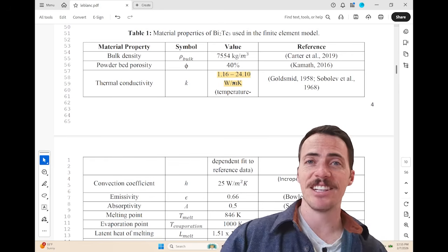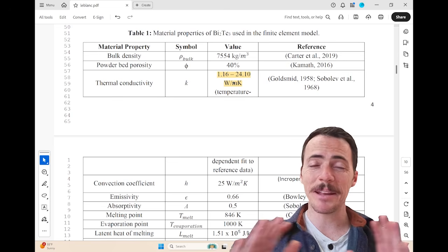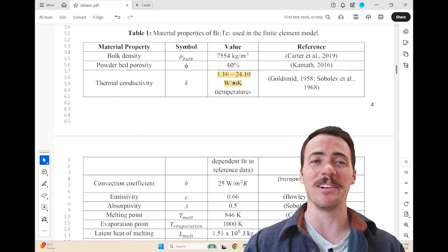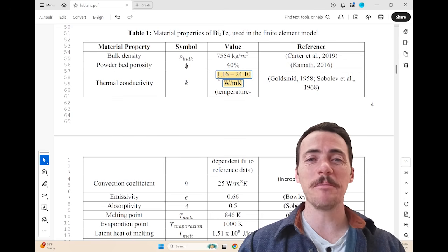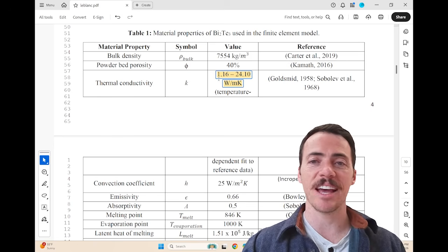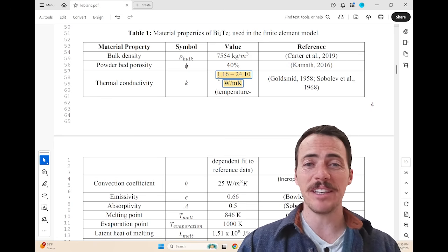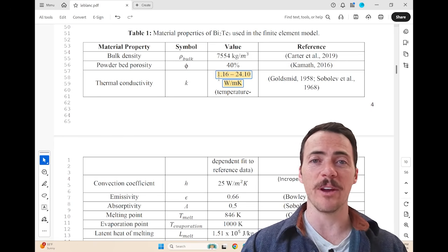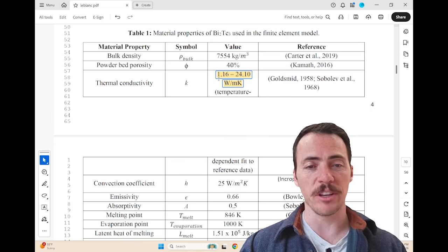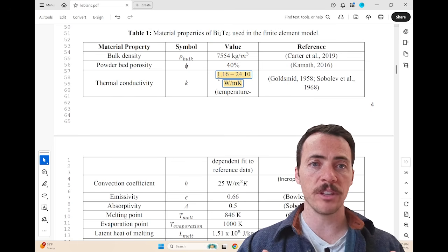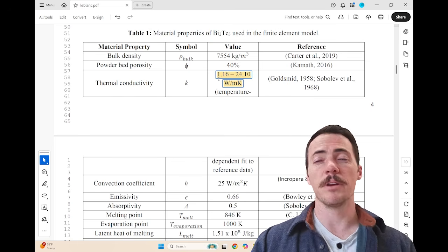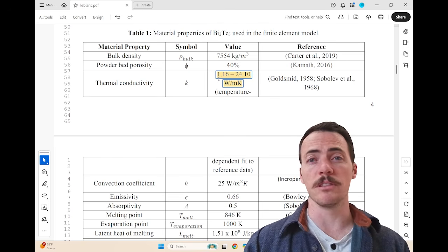The catch is that bismuth telluride is not a metal, right? It doesn't behave like a metal. Take a look at the thermal conductivity, right? It can be the reason we use it in thermoelectrics because it has low thermal conductivity. It can be down to about 1 watt per meter Kelvin, right? Very different. So to expect it to behave like a metal when you're printing it is simply not going to work. But it's not as simple as simply calibrating the model to lower thermal conductivity.